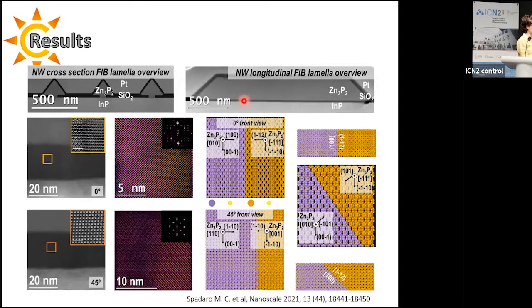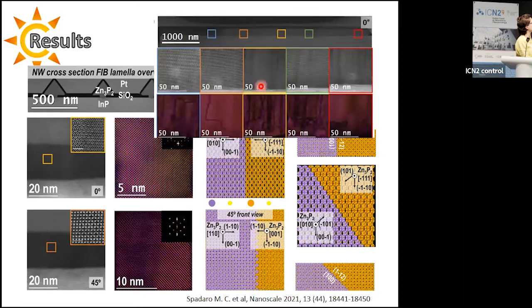When the material starts to fill the aperture trenches, many seeds are forming, and when these seeds possess the 101 facets, basically from here, the material possesses a different growth direction, which is the 110 instead of the 001, making it slightly rotated. Performing a detailed analysis on the entire length of the nanowire, we could observe that these secondary domains are not una tantum in the structure of the nanowire, but they are highly present in the length.